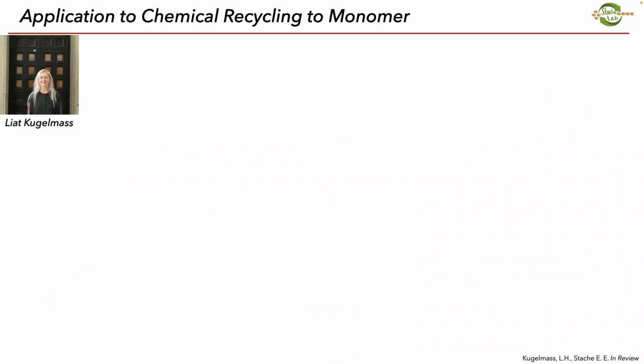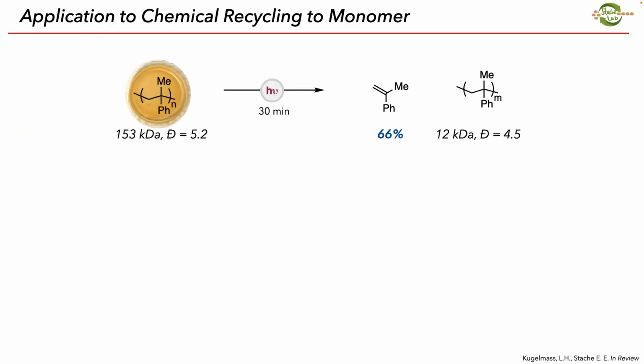monomer recovery. This is work done by Liat, a fifth-year graduate student in my lab. She solution processed a polymer and our nanoparticles to make this film. This is poly-alpha-methylstyrene. She hit it with light, and in just 30 minutes, she observed 66% conversion to the monomer. So the polymer is depolymerizing back into monomer, and then the leftover material is just oligomers of the polymer.